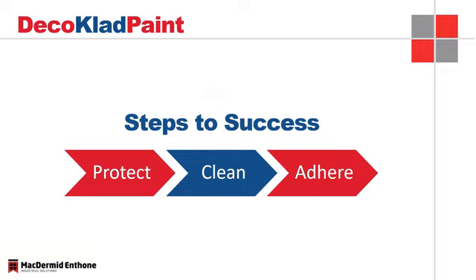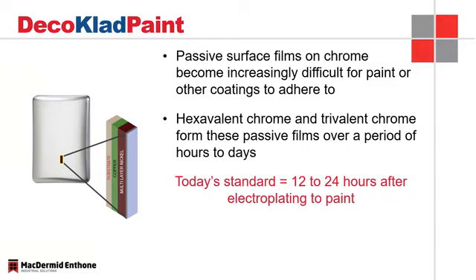So as I move into the paint side of things, there are really 3 steps for us to be able to have a successful paint on chrome process: protecting that chrome finish, making sure it is clean, and then being able to adhere that paint to that chrome as a result. So how do we do that? If I think about being able to protect that surface first, we have to talk about the chrome. One of the issues, the biggest issue that we've had in the supply chain with consistency has been related to adhesion. A lot of that is because as these parts sit, whether they're hexavalent or trivalent chrome, they form some passive surface films on the chrome. The more films that form, the more difficult it is for paint or any other coating really to adhere to that chrome. Those start to form within hours, trivalent chrome a little bit longer, over a period of days, but still we know that those films are forming, those oxide layers are building up on the surface.